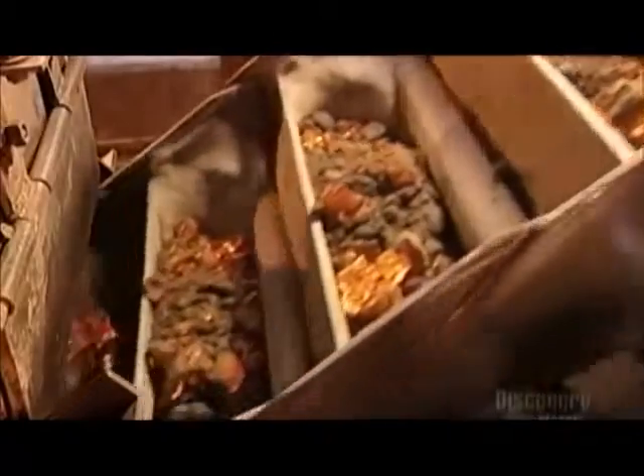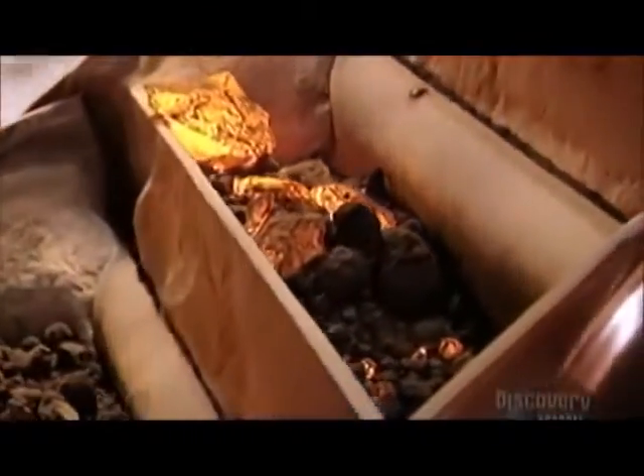As the powder approaching it reaches the 1500 degree mark, it fuses into pieces about the size of marbles. These pieces are called clinker. As the clinker leaves the kiln, large fans cool it down to between 60 and 80 degrees Celsius.